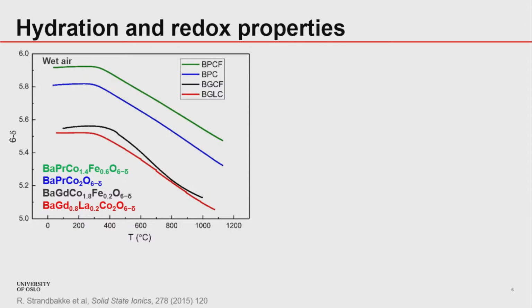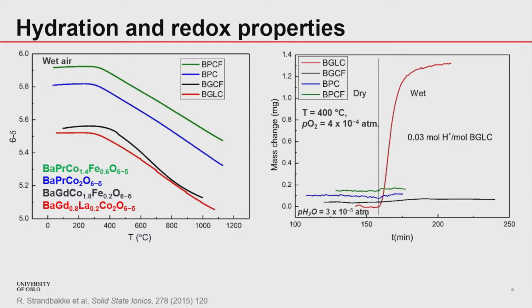Next, because of the short time, I will move to the main important thing, which is to understand the hydration properties. So now let's take all the materials and do a TG, where we are going to monitor mass change with time. What we see is that when we have a dry atmosphere at 400 degrees Celsius, PO2 of 4 × 10^-4 atmosphere, we don't see a mass change with time.